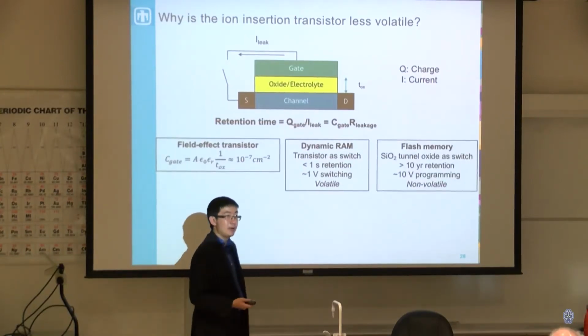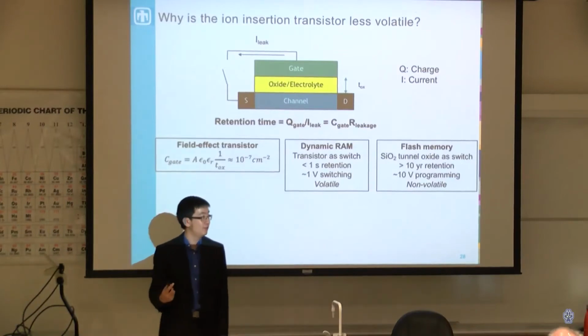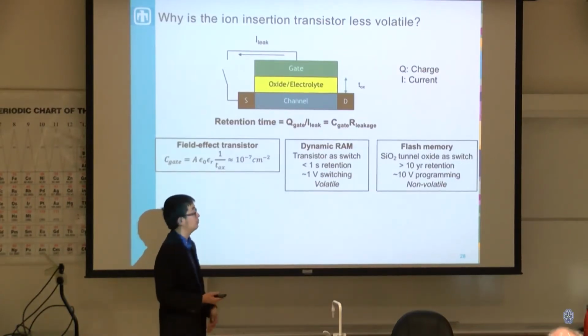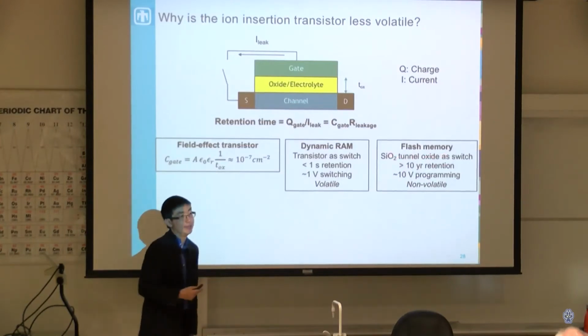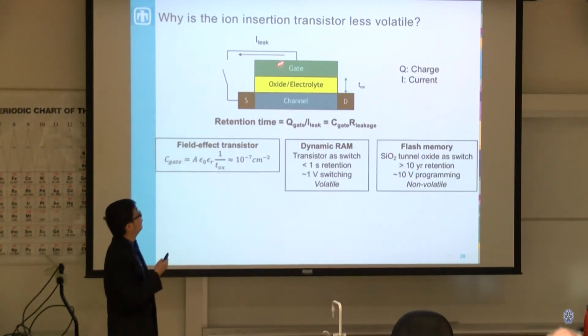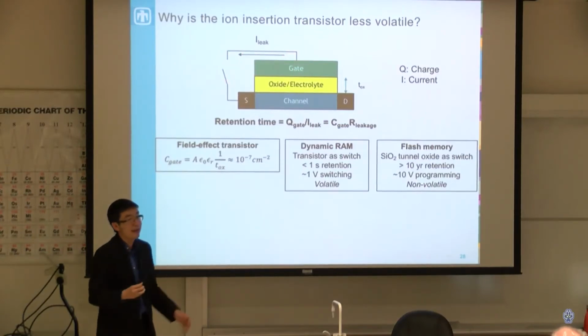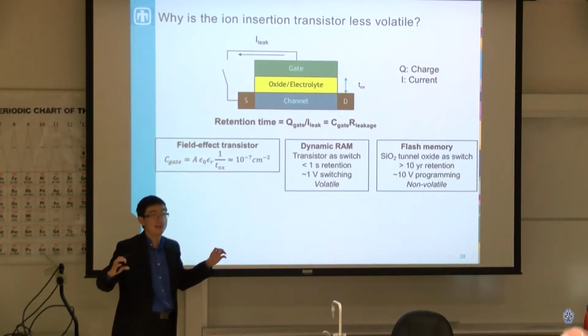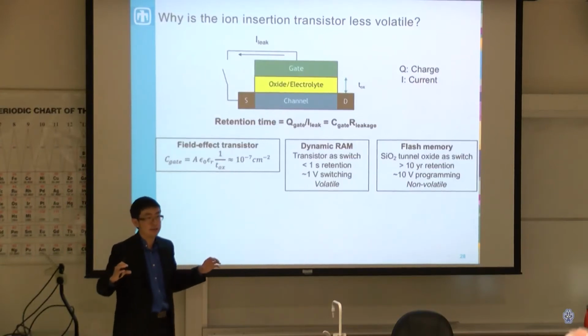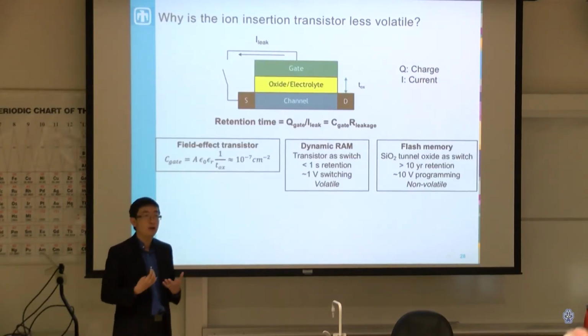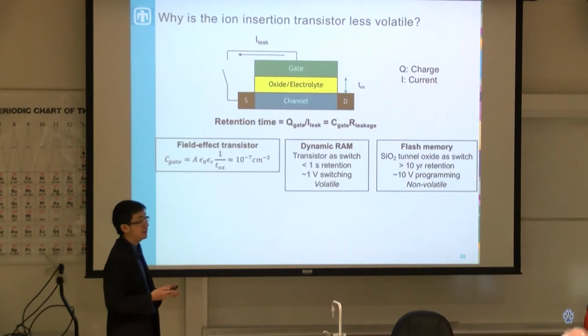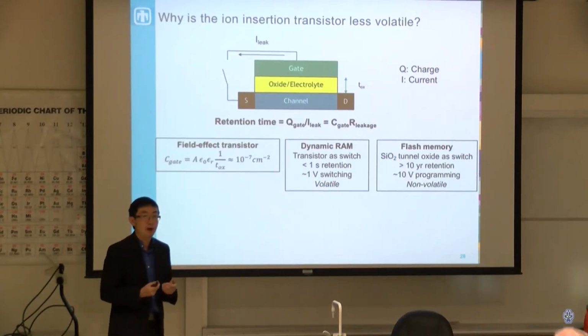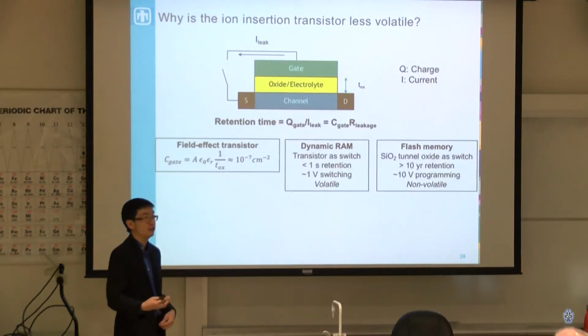If we think about flash memory, on the other hand, the ones in your USB drives and more commonly in computers nowadays, the switch is this silicon dioxide tunnel oxide. So basically you have what they call a floating gate. This gate here is not electrically connected to anything else. It's basically completely isolated by a silicon dioxide layer. So you can create a very low leakage in this device that gives you 10-year retention time. However, the problem is that because it's not electrically connected, it's also really hard to access it, to program it.